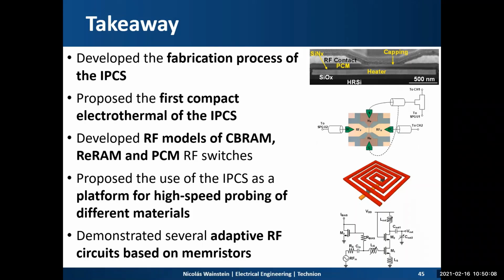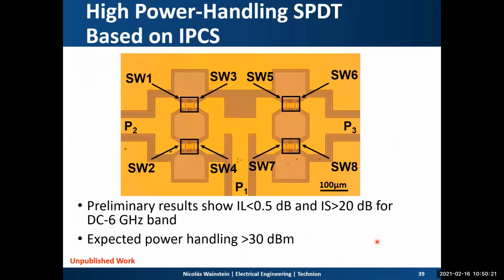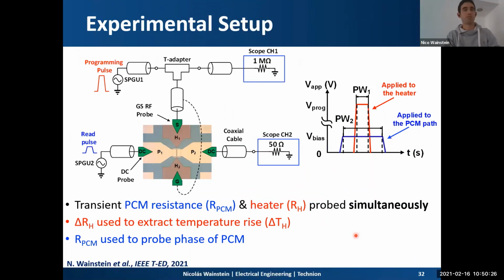Wonderful work. I want to ask if you could elaborate a little bit more about how the temperature was measured in the fast crystallization experiment you were showing. The idea here is to measure the voltage variation. First we characterize the TCR, the temperature coefficient of resistance of the heater, using a thermal stage, a chuck. Then with the TCR, we can measure the voltage variation of the heater while applying the pulse. The setup is configured for a 50 ohm network, so the variation between the 50 ohms can tell us the resistance variation of the heater. With the resistance variation, we can calculate the delta T using the TCR. So that's the temperature variation of the heater.